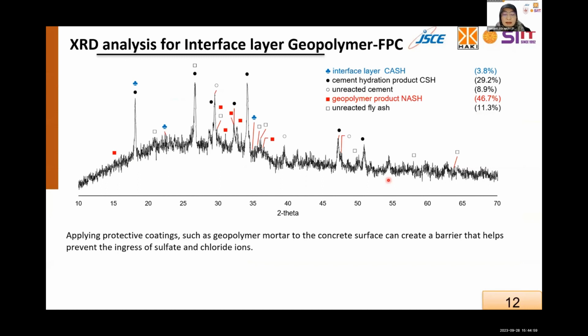And yeah, we can see by XRD analysis that the calcium alumina silicate hydrate, CASH, was formed as a product. The blue spike here is the calcium contributed by the surface of the Portland cement, while the alumina and silica are contributed by the geopolymer matrix. The red dots are minerals from the geopolymer product, and the black dots are the formation of calcium silicate hydrate. We also found some unreacted cement and fly ash material.